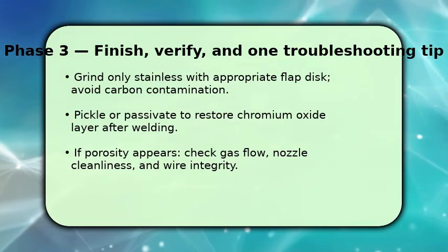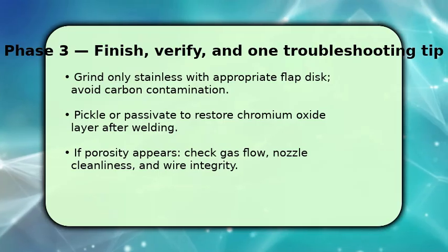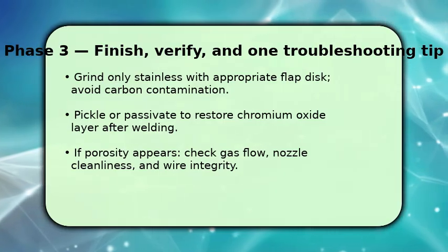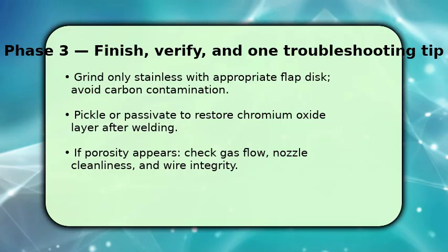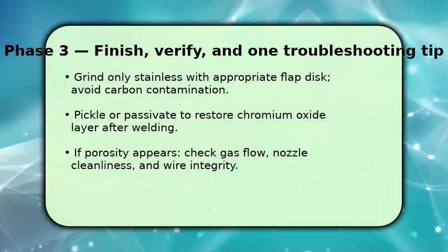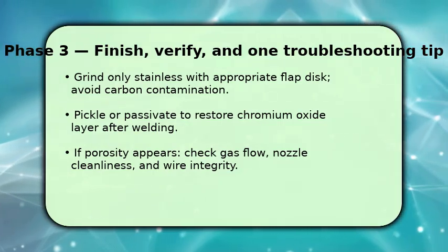If you see porosity, check shielding gas flow, ensure the nozzle and contact tip are clean, and confirm wire hasn't absorbed moisture. If distortion occurs, add clamps and redo short, cooler passes.